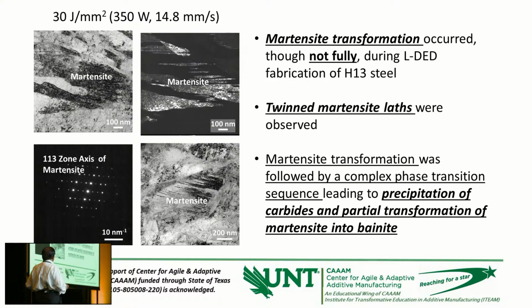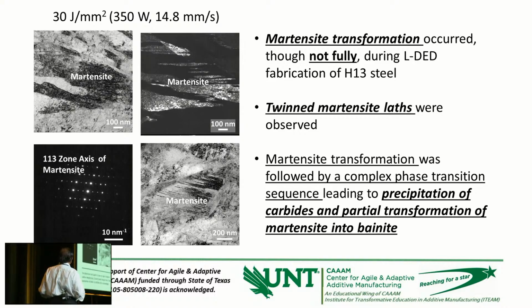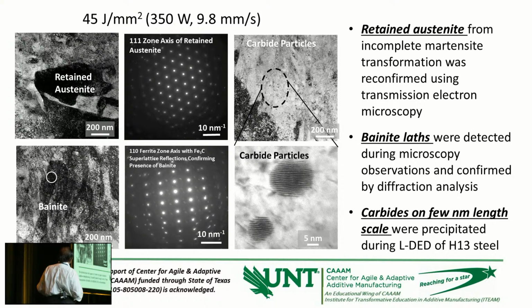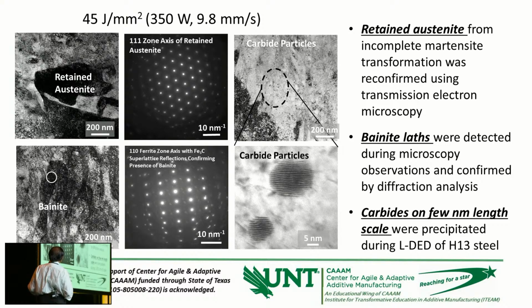Then what happens in the subsequent thermocycling, due to the layer by layer deposition and multi-track deposition, is that you get tempering of the structures, and you get carbide formation or dissociation of these carbides into bainitic structure and so on. All those things have been confirmed by these observations based on the TEM.